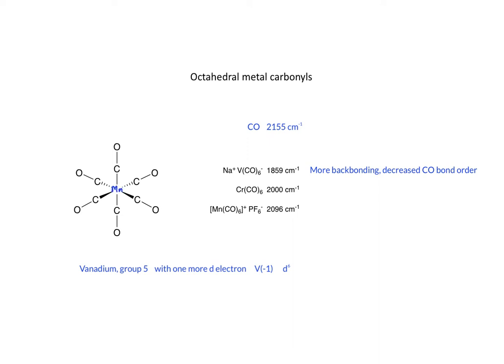For manganese, which is in group 7, if we remove an electron so that manganese is in the +1 oxidation state, manganese hexacarbonyl has a positive charge. In this case, with a positive charge on the metal center, the d electrons are held closer to the metal, are less available for back bonding. As a result, the carbon monoxide ligands have increased bond order, and this is revealed by the IR stretch of 2096 wave numbers, which is closer to a bond order of 3.